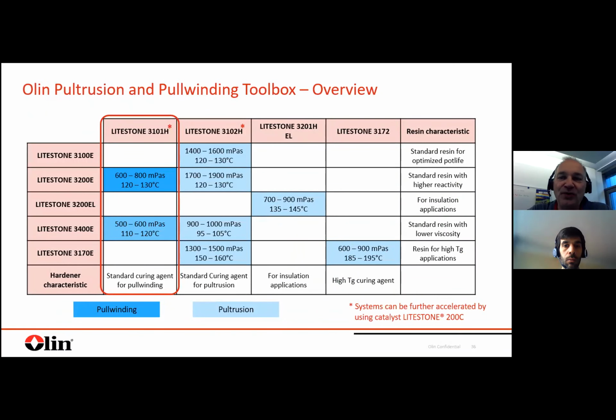At the end, we have a portfolio. I will not go into detail through this. I would only point out two things. First, if you compare, we have two standard grades, one for pull winding, a hardener 3101H, and for protrusion, the 3102H. And if you compare the two systems, you see a significant difference in the viscosity. Protrusion is higher. As mentioned, we are not targeting high line speeds, so we can accept that the viscosity is higher. The impregnation will still be possible at this line speed with this kind of viscosity. In pull winding, this can be reduced just to open the line speed potential, and it's also slightly more reactive.